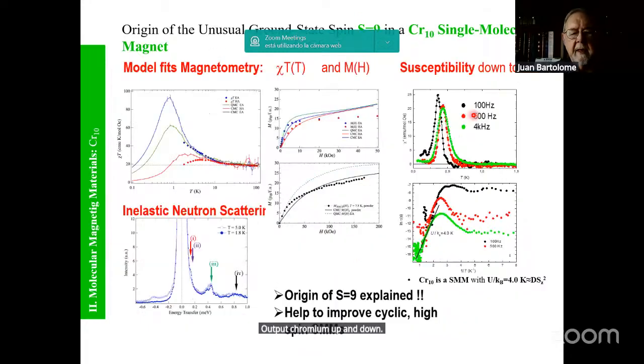And by model calculations by Monte Carlo, we could explain this magnetism as due to the molecule separating in two wings: ferromagnetically coupled chromiums at one side, and at the other side, separated by an antiferromagnetically coupled chromium up and down. Indeed, we could explain the magnetometry, susceptibility, magnetization, and inelastic neutron scattering with that technique. And at very low temperature, we could prove that this molecule behaved as a single molecule magnet, as we were expecting.